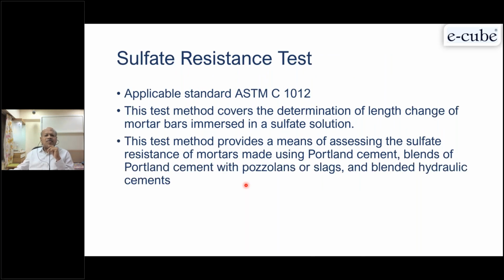Then the sulfate resistance test also takes about a year. We have to cast the sulfate specimens, mortar specimens, and immerse them in sulfate solution. Then Portland cement and various blends, blends of Portland cement or pozzolana, slag and other hydraulic materials, we can use and see how the sulfates attack. Sulfate basically reacts with aluminates to form calcium sulfoaluminates, which has the capacity to expand, and you will find there are cracks. That's why nobody advises that only OPC should be used for sulfate environments. But near the sea, sulfates are there and chlorides are there, so both tests need to be seen.